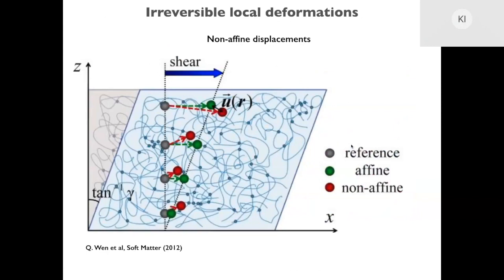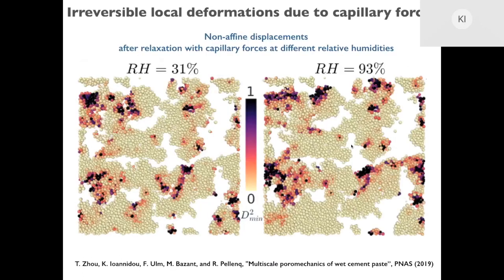Here is a cartoon to explain what nonaffine displacements are. Here we have a shear deformation of a polymer, and the affine part, you see it in green, we could reverse back if we do the opposite deformation. But what we are interested in is the red particles, the nonaffine part. So what part of the deformation is left that we cannot reverse back? Here you see exactly this type, with the particles that have the highest of this type of deformation colored in dark. In one case we have relative humidity 30%, and in the other 90%.